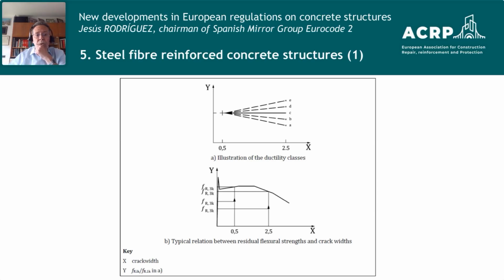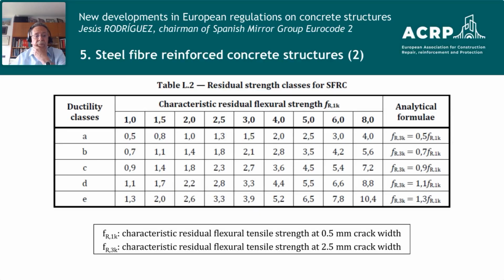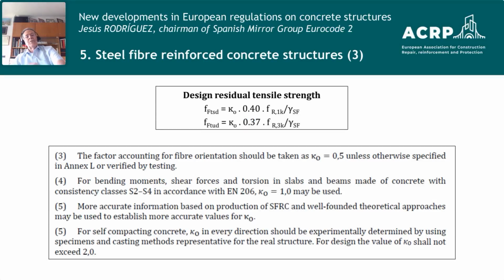So the steel fiber reinforced concrete is classified depending on the ductility that is measured in the tensile strength when a crack of 0.5 millimeters appears, or the value when the crack reaches 2.5 millimeters. And in function of these values, we have different ductility classes with the value of the tensile strength at 0.5 crack width, and the corresponding values of these fiber concretes with different ductilities at 2.5 crack width.